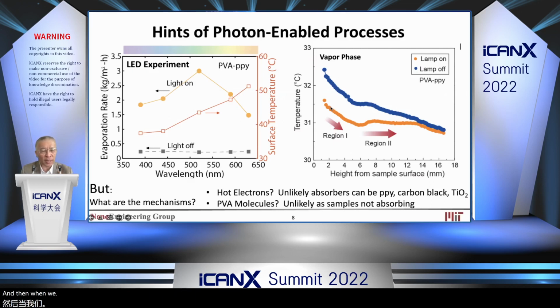And then when we look at the temperature in the vapor phase above the water, it's also very strange. The blue is when the light is turned off, and the yellow is when the light is turned on. But when the light is turned on, the temperature is lower. And then there's a region where the temperature above is actually flat. So very characteristically, very different from thermal evaporation. So what is this photon effect?